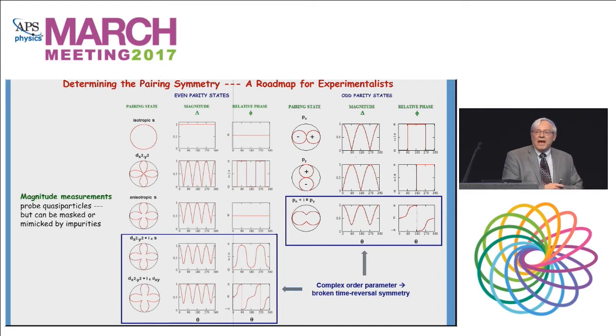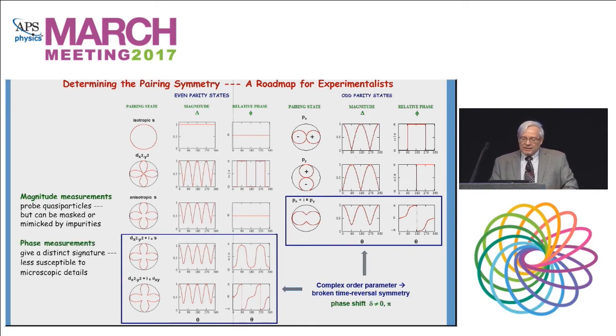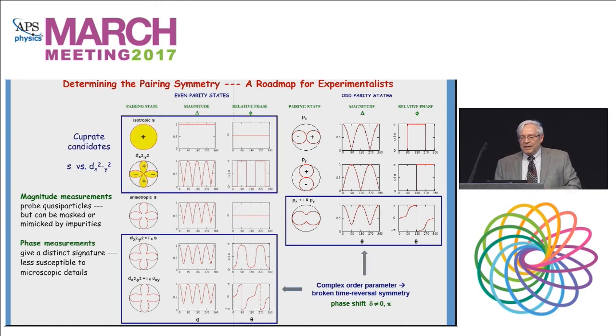But one of the problems with those kinds of measurements is because they count quasi-particles, they can very easily be fooled by things that mimic and sometimes mask the presence of nodes. So the phase measurements were really a more clear way to determine the pairing symmetry. And this is what prompted us to develop this phase interferometer technique I'm going to talk about.